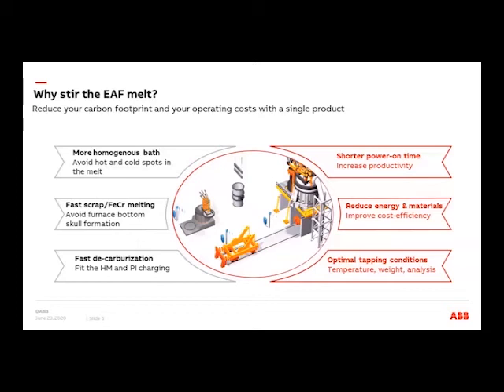The outcome of this is, of course, shorter power-on time, increased productivity, and reduced energy and consumable materials like electrode consumption, slag formers, alloy additions, and so forth. This will give a total improved cost efficiency of the electric arc furnace. We will also have smoother tapping conditions regarding the temperature, the weight, and the chemical analysis, which will then give a better outcome for the next process step, whether it will be the ladle furnace, the VOD, or the AOD converter.